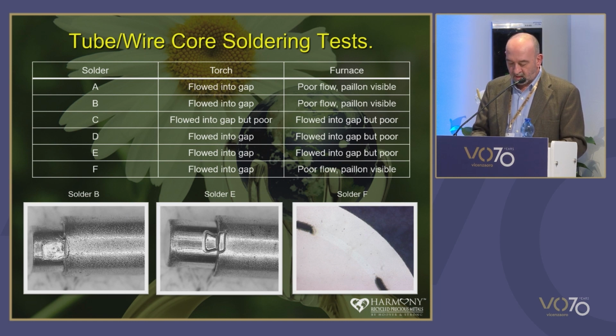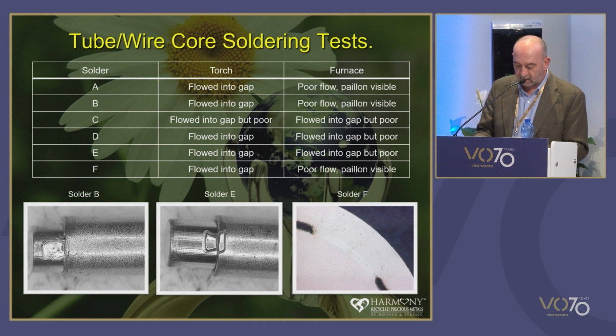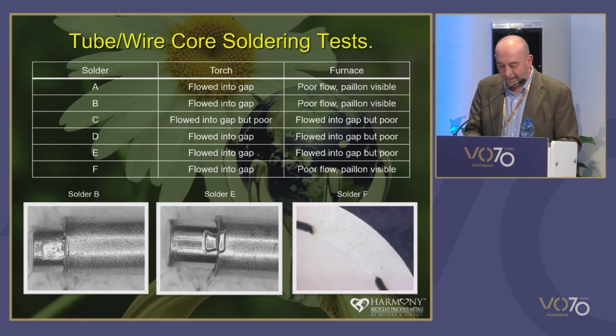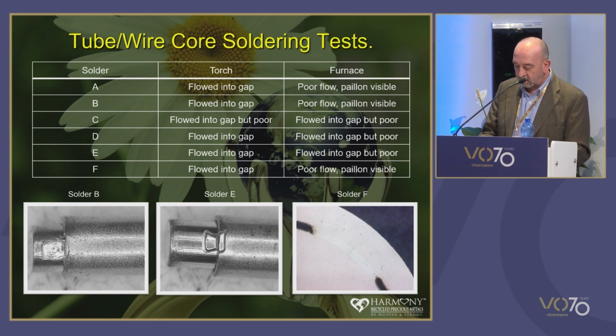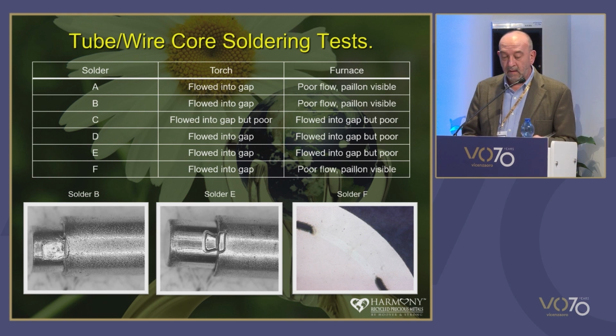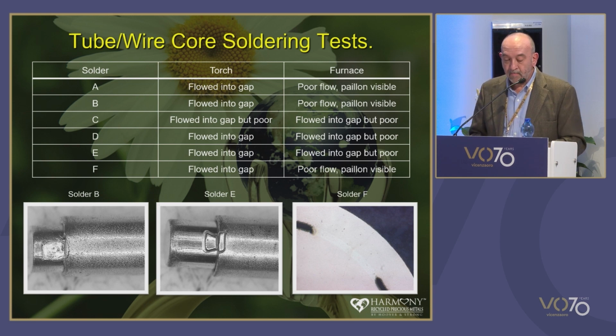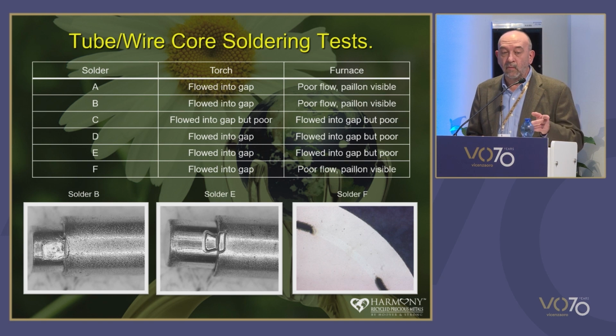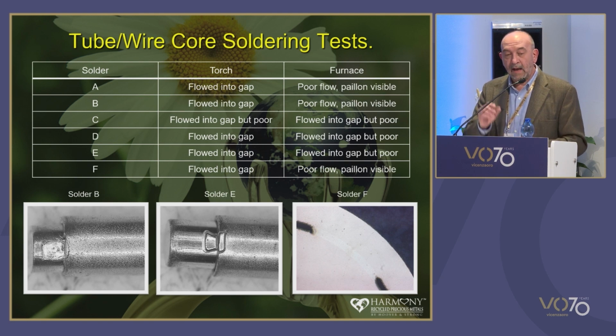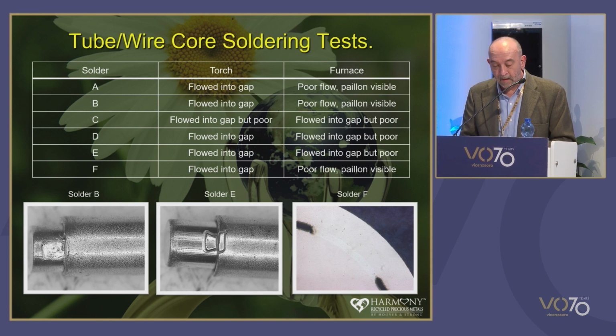I'm not really going to go into these a lot here because the test was not very good. It was a badly designed test. All it really showed us was if the gap's too big, then soldering doesn't work very well. As you can see from the microsection on the right, there's lots of voids in there. And again, we see with the white solder in the middle and solder B, we have that residual piece of solder still evident in there.